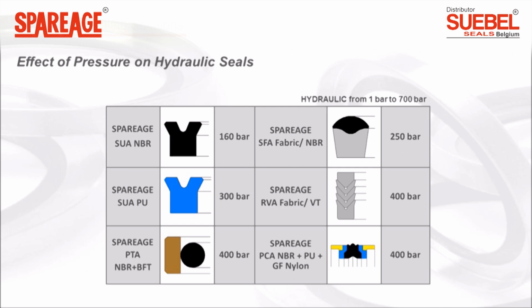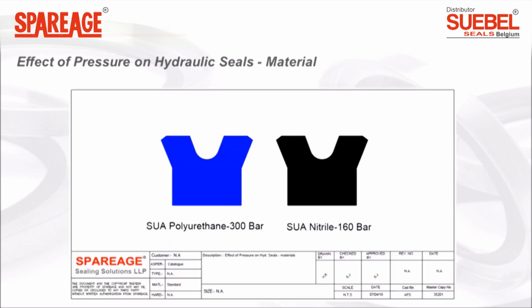The higher the Shore hardness, the more the strength of the material. But beyond 90 Shore A hardness, the material becomes brittle, therefore the maximum limit is 160 bar. But the same SUA seal made in polyurethane can withstand a pressure of 300 bar due to higher tensile strength in its virgin state without filler or fabric reinforcements.